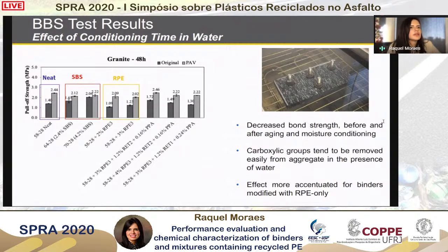Because, again, since the carboxylic acid groups are developed with oxidative aging, which are favorable for the dry state, they are unfavorable when we consider moisture conditioning, because they can be removed very easily in the presence of water. And we see that this effect is more accentuated for the binders modified with the recycled plastic by itself.